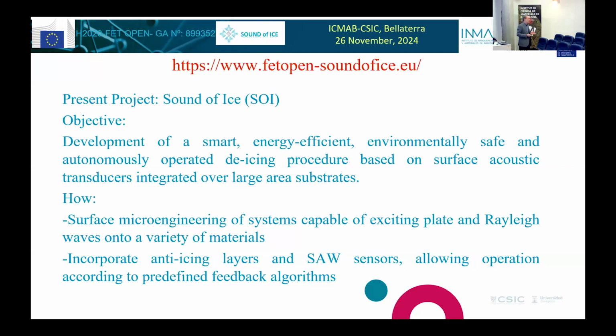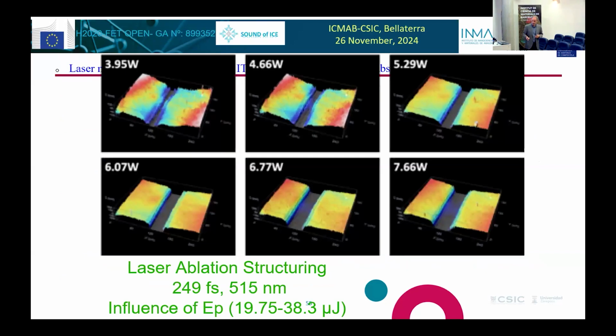So they try to find solutions for this, and one of the things we did, this is the second project we do, is to change the surface so that ice can be lifted off more easily or not form. Not forming is difficult because of how it forms, but lift off would be a good help because at the moment they use a lot of energy to melt the ice and remove it. So the idea is to decrease the amount of energy needed to do that. For that, we can make circuits over a complex structure, for example, where you have ITO, indium tin oxide, over glass.